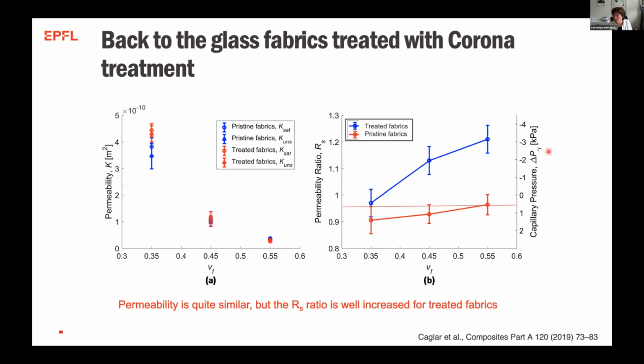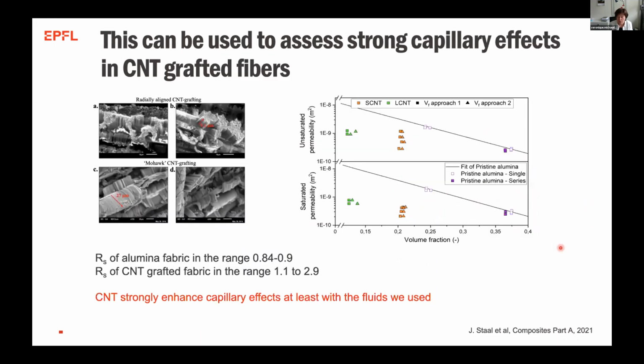And if we calculate the capillary pressure, which we extrapolated from this RS value, we see that the capillary pressure is positive. Here it's inverted, otherwise it doesn't work. So here it becomes positive, and here it's negative. And interestingly, as compared to what we had with the simple capillary rising experiment, where we had very low values, here we can get to values that are a bit higher, also 3, 4. So it works.